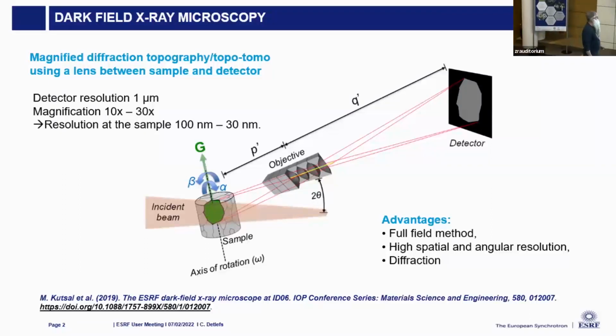Dark field microscopy is a technique that we've been developing since about 2013-14, so it's fairly new. It's a combination of X-ray topography, so making images of diffracting crystals or crystalline elements in samples, but putting an X-ray objective in between the sample and the detector. That has several effects. One is that it magnifies the image, so we can reach a spatial resolution on the order of 100, 150 nanometers.